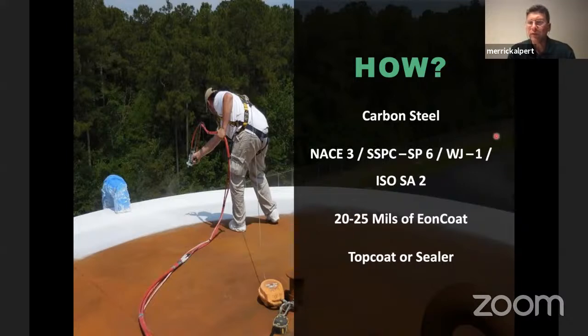Then for surface preparation, we're looking for a basic commercial blast, much cheaper, much less expensive, much faster than taking it to white metal and trying to hold the blast. People blast the entire tank or pipeline section or section of offshore platform, and then they apply the coating. We apply 20 to 25 mils. That's about 508 to 635 microns. And then for an atmospheric use, like a tank like this, you would use a top coat. But of course, in the CUI environment or for the weldable coating, we would not use any top coat. It's a single coat system.